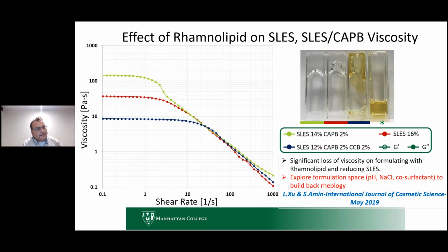But from the perspective of understanding this, we understood that the whole aspect has to do with electrostatic interaction. There are charged species in here, right? There is an anionic SLES, there's a zwitterionic CAPB, and there's a rhamnolipid which fluctuates a little bit like the zwitterionic based on pH, going from slightly anionic to slightly non-ionic. So there are these fluctuations which go on when you start to change the pH. Under different pH conditions, different electrolyte conditions and different ratios of these surfactants, you will get different behaviors.